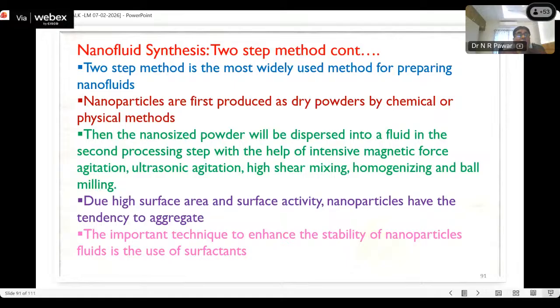Nowadays we use this for the synthesis of this material. And now this nano-sized powder will be dispersed into the base fluid in the second processing step with the help of intensive magnetic force agitation, ultrasonic agitation, high shear mixing, or any one of that we may use. Then, due to the high surface area and surface activity, nanoparticles have the tendency to aggregate. The important technique to enhance the stability of nanoparticle fluid is the use of surfactants.